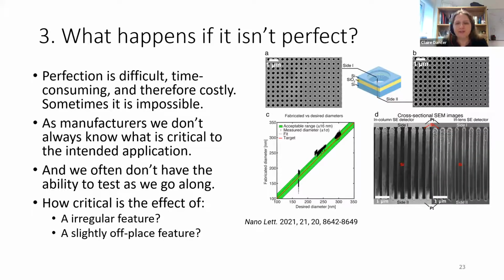I found this paper recently, and it's partly what's inspired this part of the talk. This is a paper from Capasso's group, and they were making holes again in silicon, making this metasurface. These are really quite deep holes, which is quite interesting for the aspect ratio. You can see the cross section here, they're coming down. This is entirely what I would expect, because you've got a certain degree of drift, so you get some movement while you're doing the focused ion beam work and removing the material. You get some inconsistencies in the shapes of these holes. And my question is, how much is that acceptable? How much of this is okay?